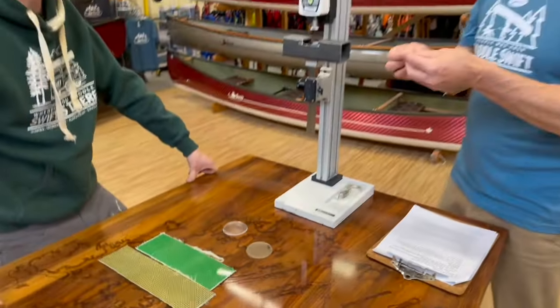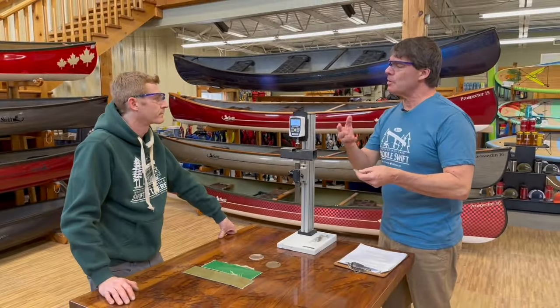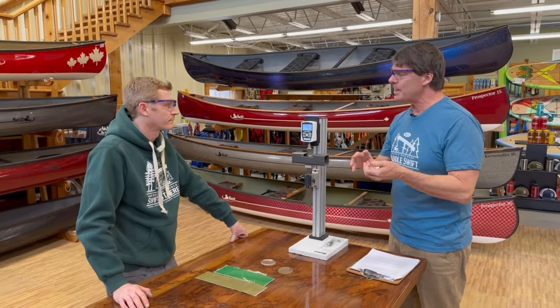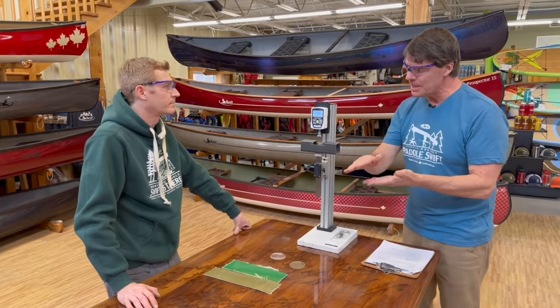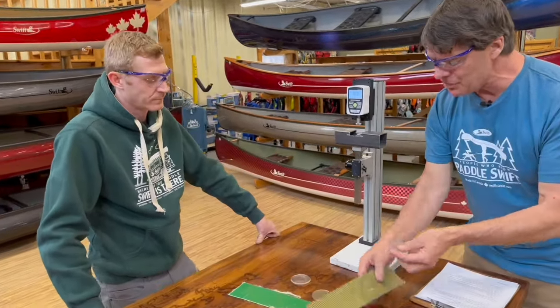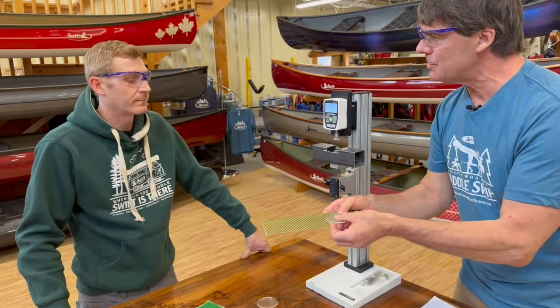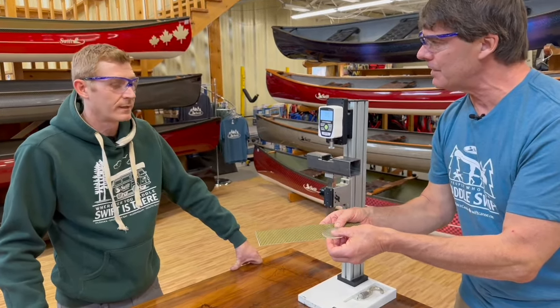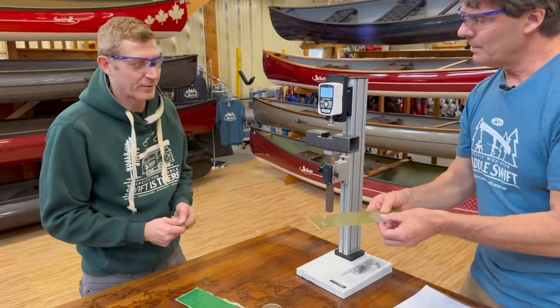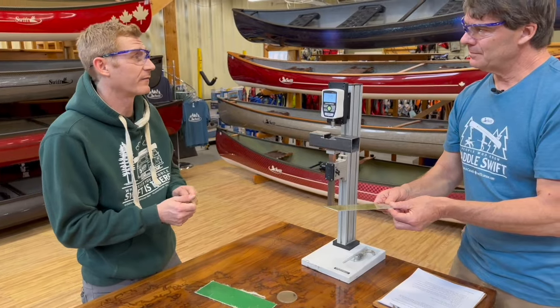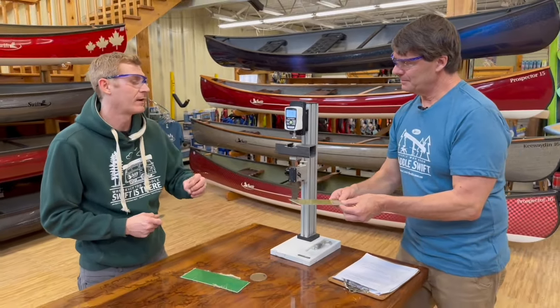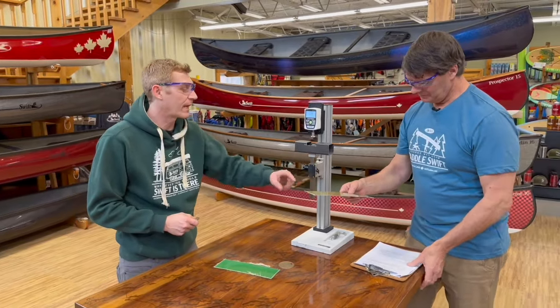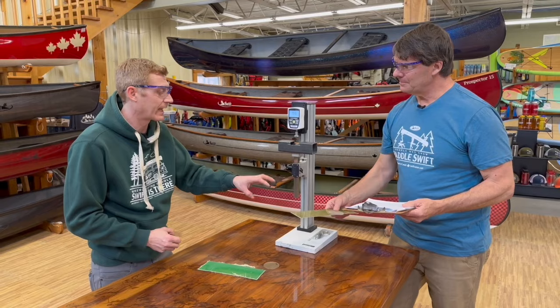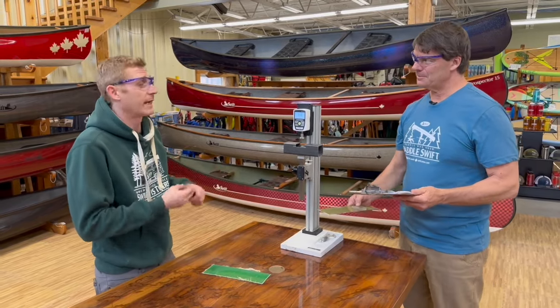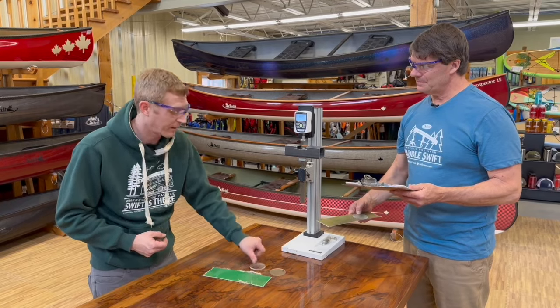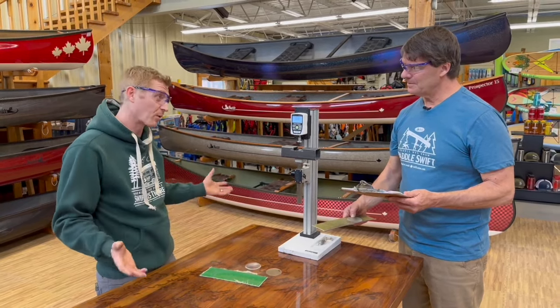And Matt, so people really clearly understand, there's a term, composites. Composites is a combination. For us, it's the UV shield, the resin, and the cloth. The cloth adds so much to the strength of the resin system and the UV shield. It's the combination of everything. Like Bill said, without the cloth, once the resin gets to its breaking point, it's just broken. Whereas with things like Kevlar that has incredible cut and abrasion resistance, you could actually destroy the resin matrix within that laminate, and the laminate could still hold together, and you could continue paddling your boat. If it were just resin, it would break, and then your boat would just be broken forever.